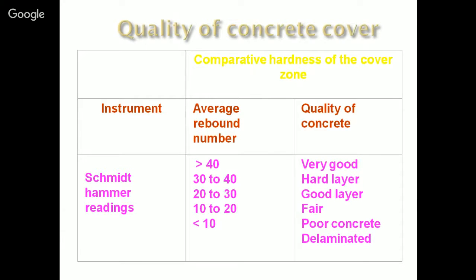As I said, I was giving the example. We had a pier being constructed, and when the testing of that pier was done, it was found that one particular lot of cement was giving low strength. It was a pier about 20 meters in height and 7 by 7 meters in width. It was not known where that poor quality cement had been used, so the best available method was the rebound hammer. Using the rebound hammer test, the stretch where that low-strength cement was used was identified and rehabilitated.